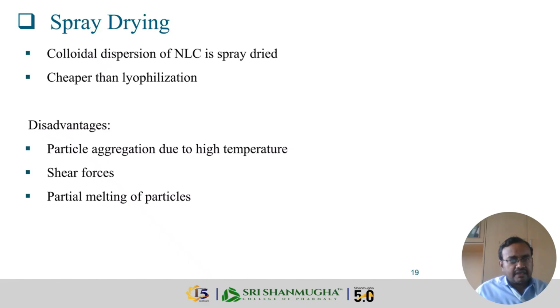Then the spray drying technique, where the colloidal dispersion of nanostructured lipid carrier is spray dried. It is cheaper than the lyophilization technique. When compared to all other methods, this is the easiest and cheapest method. It also has some drawbacks. Particle aggregation occurs due to the high temperature and shear forces, and partial melting of the particles. Only the particles are not completely melted with the lipids.